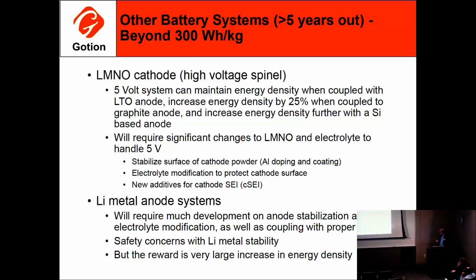And finally, last but not least, the lithium metal anode systems. They have long work to do. There's a bad history with these from back in the 1990s when the first rechargeable lithium metal anode cells came out, and they caused a lot of problems. So there's a bad taste in a lot of people's mouths with these materials, but there's been a lot of good work done recently about how to stabilize that lithium metal anode. The reward at the end of the day is really high with that material, because your energy density will go up significantly if you can take that lithium metal anode and put that into place.